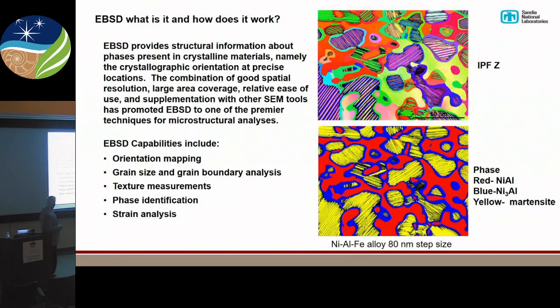EBSD right now, it's great for orientation mapping as shown here. So this map represents the orientation of those various phases using a color key, and I'll talk about that in a bit. We can talk about grain size and grain boundary analysis if you're interested. And by grain boundary analysis, I'm talking about also orientation relationships between phases. So we can study those quite nicely.